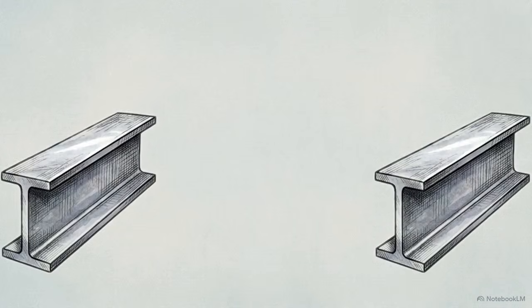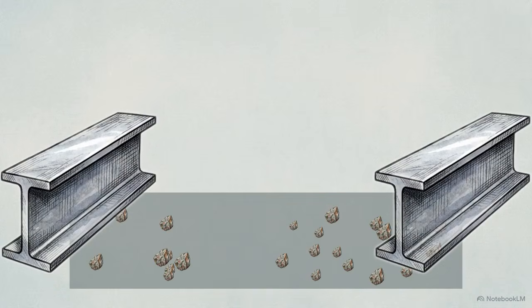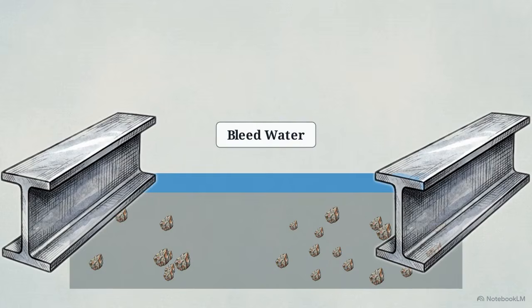To prevent this, a specialized hardware stack is layered onto the wet concrete immediately after the screed finishes leveling. The first layer of this stack is a specialized filter media that descends directly over the wet concrete surface, making contact with the pooled water. This filter mesh operates under strict tolerances. It allows pure water molecules to pass through while physically blocking fine sand and cement paste.